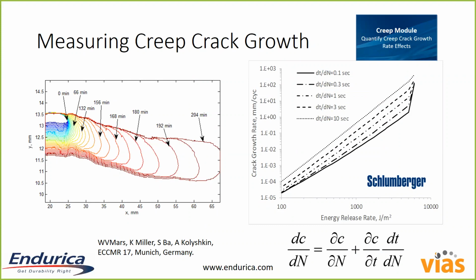And the purpose of this experiment: sometimes in applications where you have very large loads applied over a very long time, the crack growth rate behavior of the rubber can become not only cycle dependent but also time dependent, because a crack can grow very slowly in rubber as a function of time.